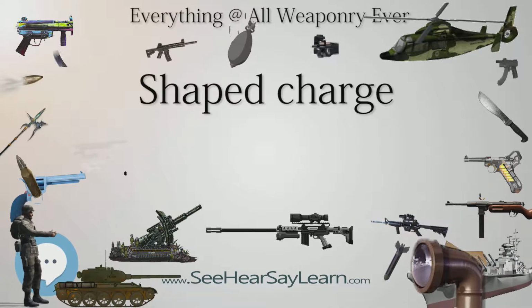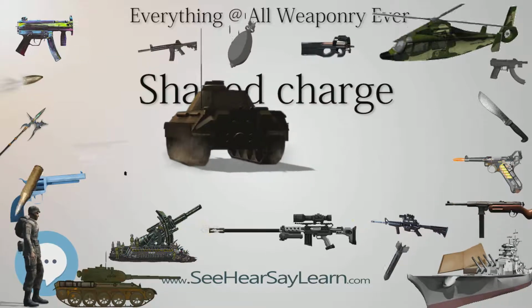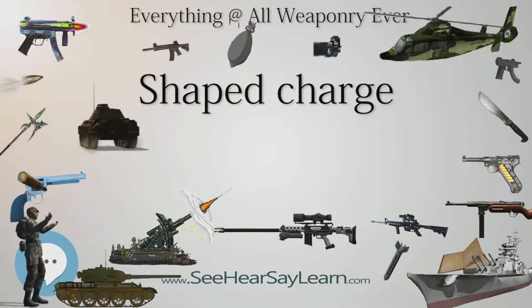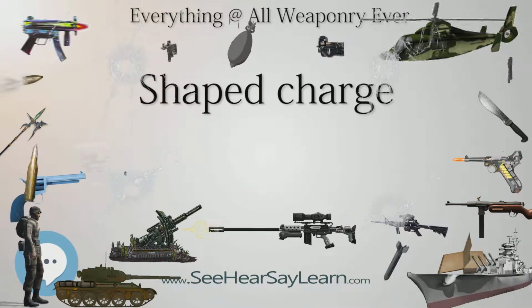In early anti-tank weapons, copper was used as a liner material. Later, in the 1970s, it was found tantalum is superior to copper, due to its much higher density and very high ductility at high strain rates. Other high-density metals and alloys tend to have drawbacks in terms of price, toxicity, radioactivity, or lack of ductility. For the deepest penetrations, pure metals yield the best results, because they display the greatest ductility, which delays the breakup of the jet into particles as it stretches.